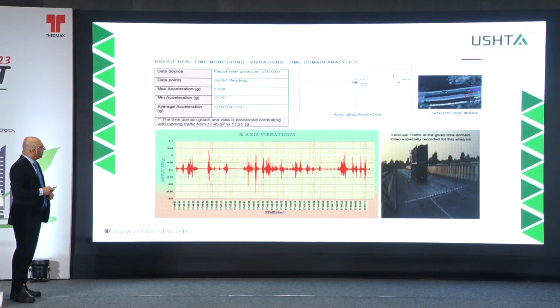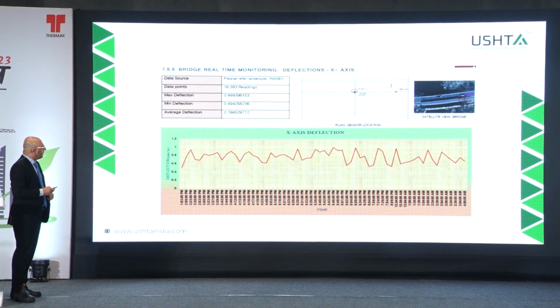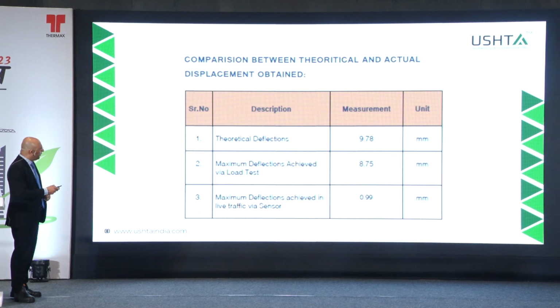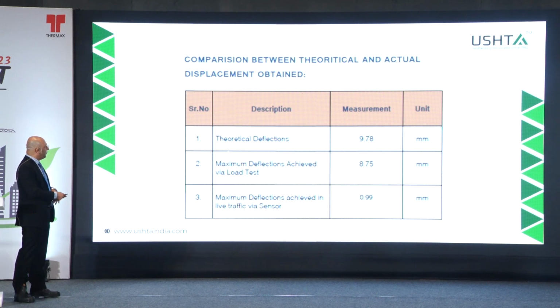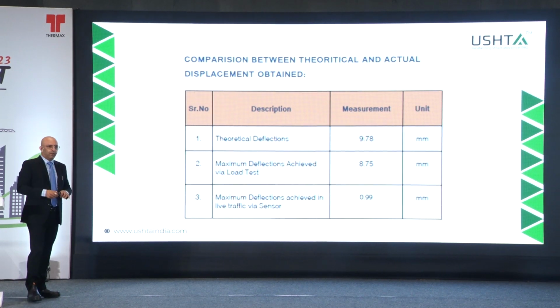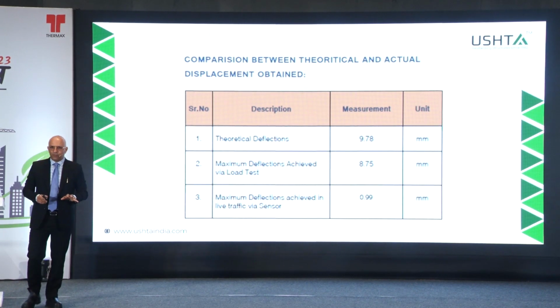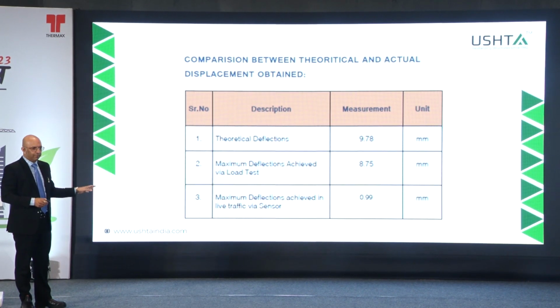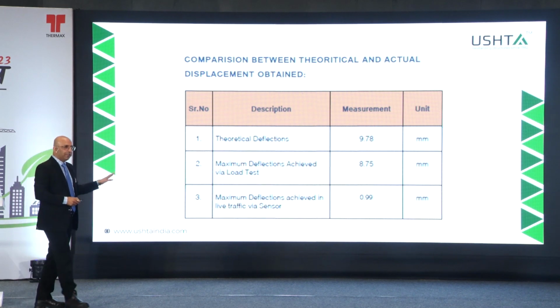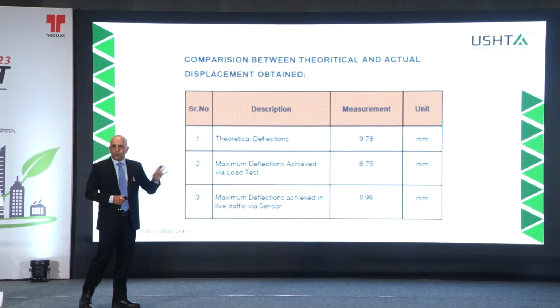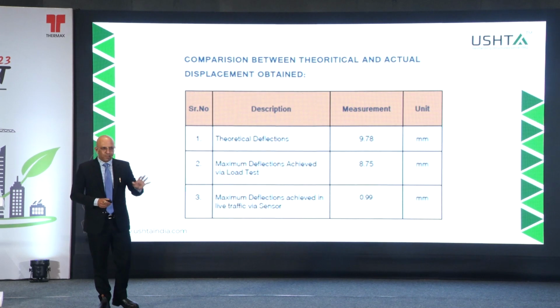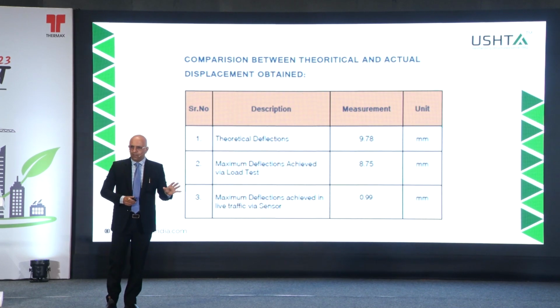And we realized, this is one of the properties we are talking about, theoretical deflection was 9.78. That attained while we did the load test was 8.75, and in the worst possible traffic condition it was just 0.99. So we aren't using even 10% of the capacity, and we are talking of retrofitting. So sometimes, as I mentioned, less is more.